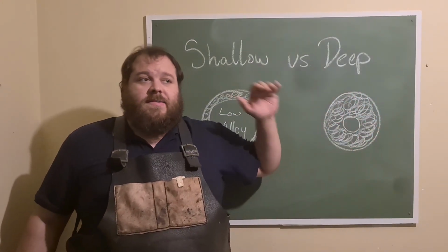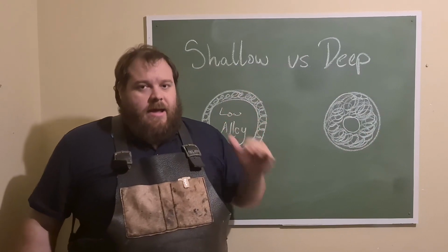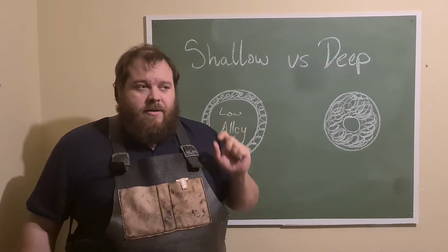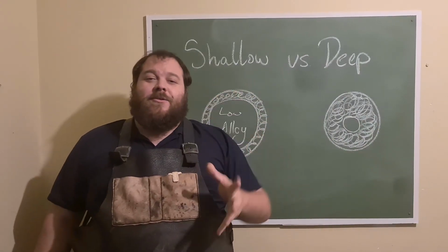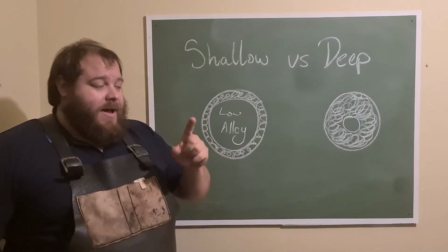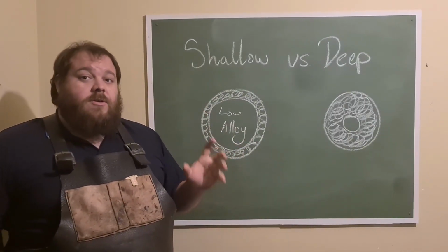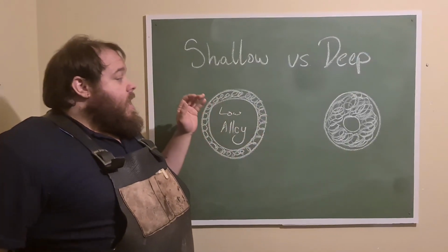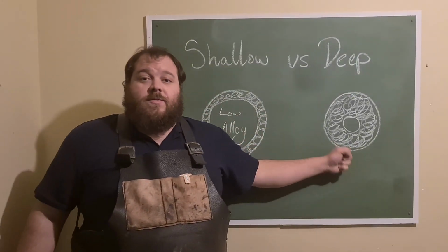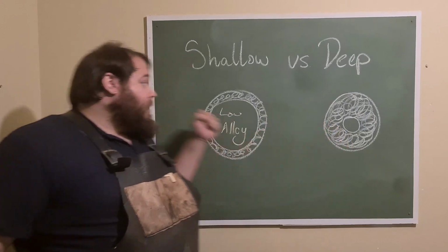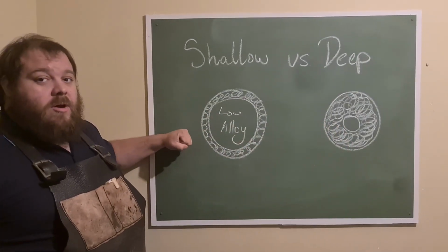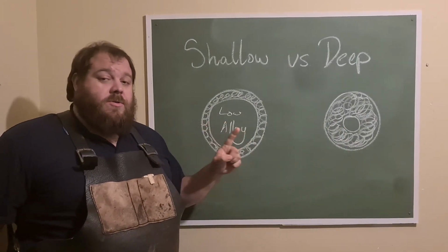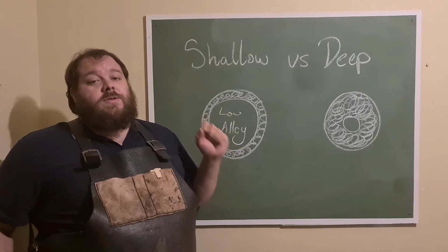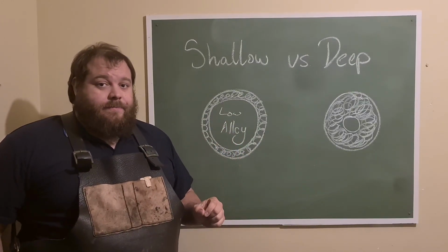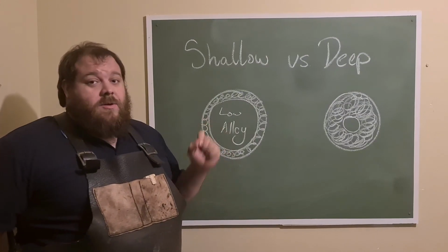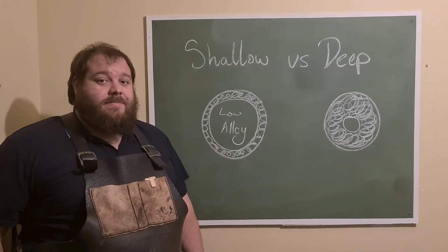This is why stainless steels technically can't get a Hamon. There are specific stainless steels that can, and I know there will be people who get in the comment section and tell me that they can, but for the most part, stainless steels cannot get a Hamon. So the reason for that is because of the high chromium levels, which cause carbide precipitation. But if we want to get a shallow hardening steel, what we don't need is a hypereutectoid steel. What we do need is a low alloy steel. So with this in mind, let's talk about some ideal alloys.